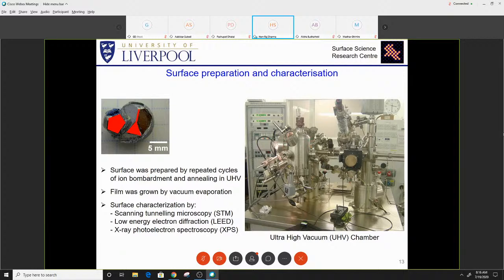Since these samples are not available commercially, we have to rely on our collaborators, especially for samples from the USA or Germany. Once we have the sample, we slice it along the desired crystal axes. There are three possible axes, for example in a five-fold; we have studied two-fold and three-fold. Once we slice it and polish it using diamond paste, we put the sample in